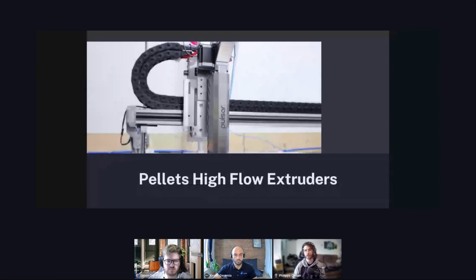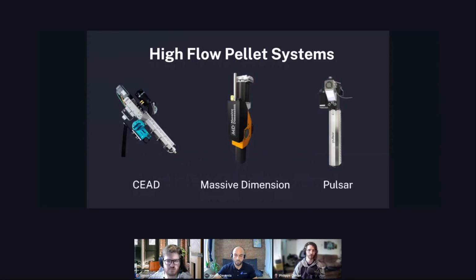Now let's talk about the pellets extruder. It's another good way to increase profitability in material extrusion. An extrusion screw is able to melt polymer much more efficiently, thus can reach much higher flow rates. Using pellets has another benefit. The cost of raw material is on average 8 times lower when using virgin resins and even lower when using recycled polymers. Here are some high-flow extrusion systems available on the market.